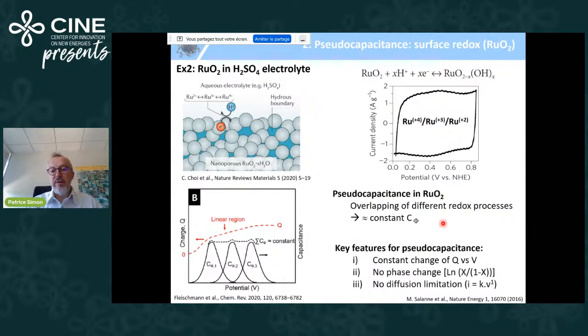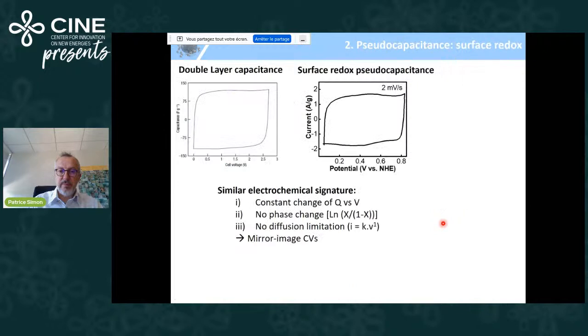And this overlap gives you this envelope here, where the pseudocapacitance is constant with the potential. So the key feature for pseudocapacitance is a constant change of Q versus V, no phase change. Again, it's a one-phase system. It's a continuous intercalation or redox intercalation of cation in the material, or a continuous change in the redox state of the material, and there is no diffusion limitation. So this surface redox capacitance, again, is this one, and you have to keep in mind that you end up with mirror image CVs with these materials.